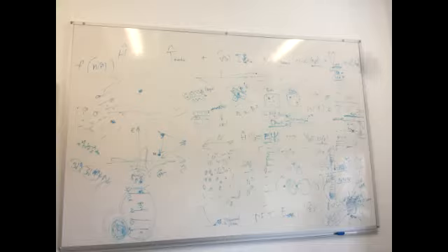So we need tighter densities, basically. Magnetic systems are problematic because this configuration and this configuration and this configuration are very, very close in energy. So when you solve for DFT, it will try to find the lowest energy minimum, but it's hard because it's a multi-dimensional space.